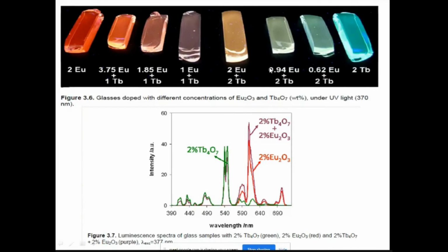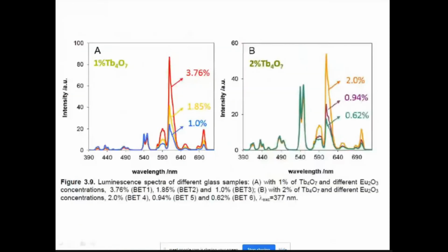So there is plenty of research in glasses, and these glasses can be developed very easily, even in degree colleges with minimum facility, where a furnace is sufficient, and an alumina crucible or silica crucible is sufficient. Phosphates are cheap, silicates are cheap. The only expensive part is rare earth ions, but you need only 5 to 10 grams. So depending upon the rare earth ion concentration, combination, and host matrix, you can tune from red to green or in between. And these are the emission spectra.